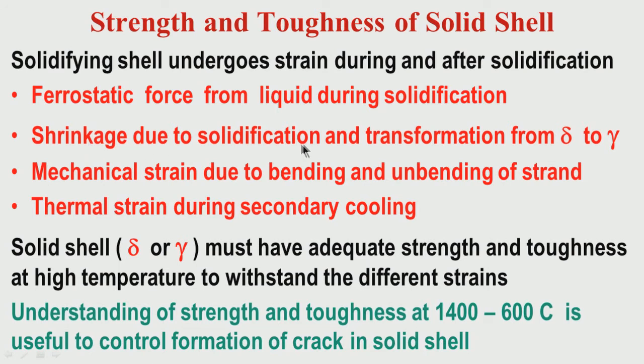Then there will be shrinkage during solidification — in steel, shrinkage occurs when solidification takes place. Additionally, there will be shrinkage from the transformation of delta to gamma. For certain grades, you initially have delta then gamma; for others, only gamma. What is important is when and at what temperature the delta-to-gamma transformation takes place and to what extent, as these may also add to the shrinkage value.